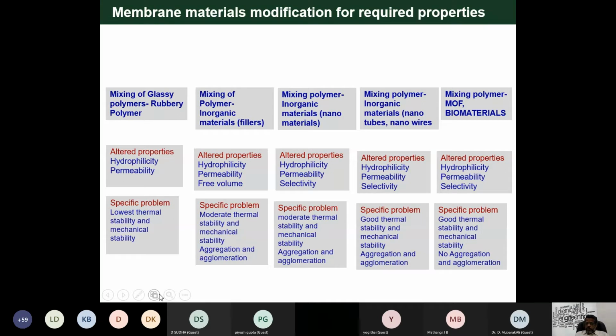But there is some problem: lower thermal stability and mechanical stability occur when we do this. Then people moved on to what they call fillers, inorganic materials like alumina and silica. We started to work on this in 2007, and we have published in a journal. We incorporated alumina and silica as fillers into polymer to make the membranes. Here we improved hydrophilicity, permeability, and free volume between the inorganic and organic phases. But still, we had problems of moderate thermal stability, mechanical stability, and aggregation of the fillers.